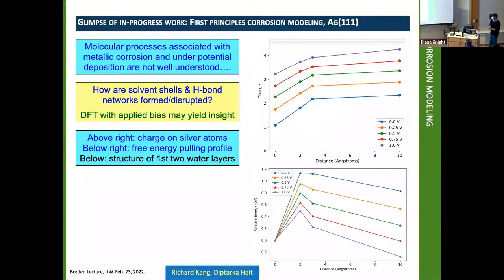What about the pulling profile? This is the profile for pulling a silver atom out from a silver 111 surface. This looks really quite encouraging to me. We see that there is a barrier associated with pulling a silver atom out at all applied biases, but that barrier falls by roughly a factor of 2 as we go from 0 volt to +1 volt as we charge the surface positive. And most importantly, the thermodynamics goes from endergonic at the low applied biases to exergonic at the highest applied bias of +1 volt.